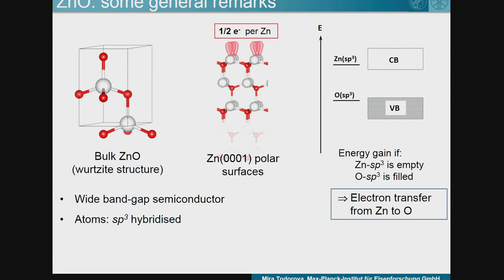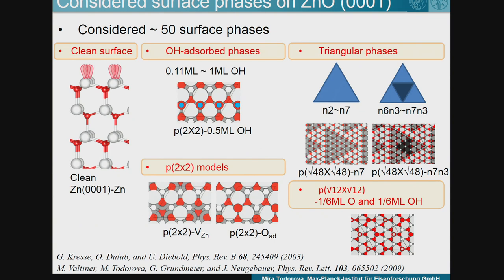And I'll be looking at the zinc terminated polar 0001 surface. And as indicated here, each of these atoms has a dangling bond which is filled with half an electron. So we do have a surface charge on this surface. And because the zinc sp3 hybrids are high in energy and oxygen hybrids are low in energy, there is a drive to transfer the zinc electron to the oxygen and thereby end up here with an empty and here with a filled dangling bond. And this is what we also find drives reconstructions at the surface.